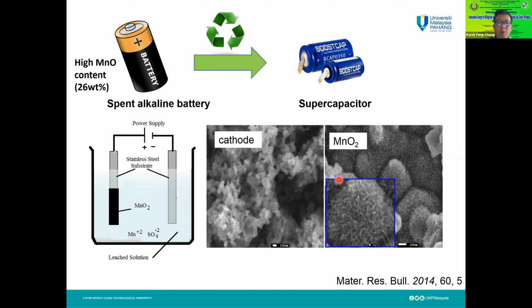You can see in terms of morphology, this is the spent battery. The morphology for the manganese oxide seems like they come together. But after we do the electrochemical and the chemical treatment, we can reactivate the manganese oxide into a very nice nano flower, nano petal shape. So for this, we check the oxidation state of this manganese oxide. It reverts back to manganese 4+, which means that we remain electrochemically active. And then the surface area is also increased because right now it exists as a flower shape.